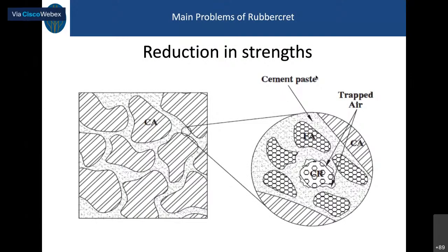But what's the problem with that? When we add the crumb rubber from scrap tires, due to the hydrophobic nature of crumb rubber, it repels water and entraps air on its surface. So the interfacial transition zone between the hardened cement matrix and the crumb rubber particles has tiny voids or becomes thick. During load application, it causes internal stresses. These stresses cause cracks, which lead to premature failure of the rubbercrete.